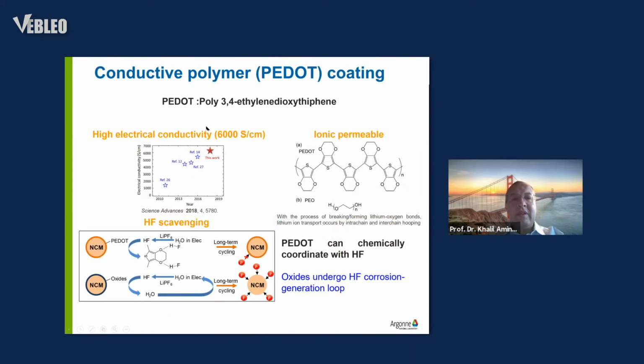This is the conductivity of the PEDOT. This is our work, and you can see it's highly conductive electronically. The PEDOT structure shown here is ionically permeable by hopping from one oxygen to another, similar to the PEO concept. We also find out that the PEDOT is an HF scavenger.